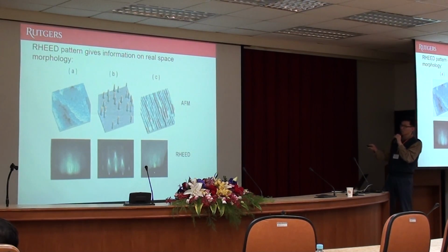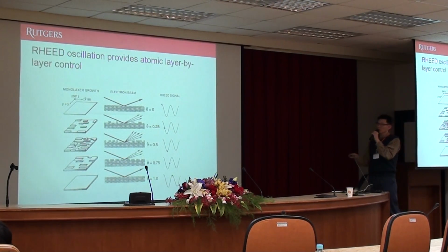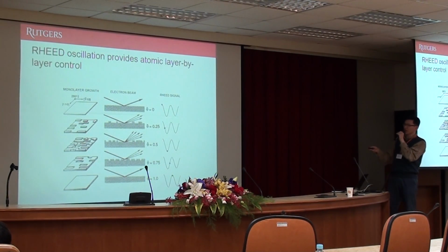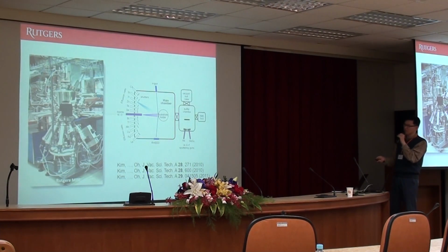But in MBE, because of RHEED, you can tell right away, you can fix it. So that's another good advantage. Depending on the morphology, your RHEED pattern can have characteristic patterns, so you can roughly guess in your head what the real space morphology would be like. Also, RHEED provides atomic layer control because of oscillations. One oscillation corresponds to one molecular layer, so that provides another control. So this is our MBE system we use.